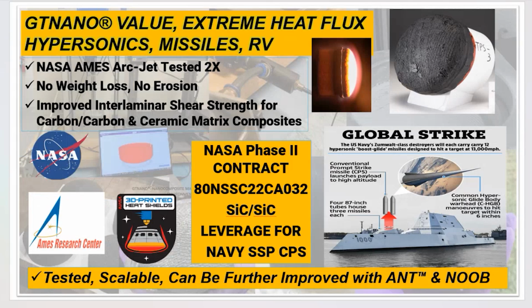For NASA, this is the fabric ceramic matrix composite prepreg. This is a SiC-SiC composite. We arc jet tested at Ames Research Center. We tested this part more than once. We demonstrated that it didn't lose any weight, it didn't erode, and that it was therefore reusable. The Phase II contract, I showed you, that was the scale up, and that was the robotic manufacturing part of the system. The same technology is relevant to global strike.